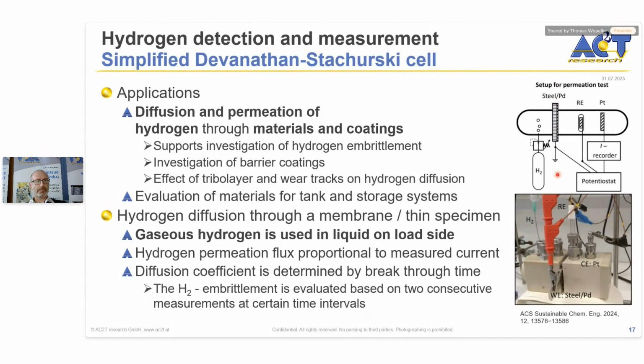And by measuring the electrical current between the steel electrode and the platinum electrode, you can determine the hydrogen content, which is proportional to the electrical current, and thereby you can determine the diffusion coefficient of the steel by determining the breakthrough time through the steel membrane. So the time the hydrogen needs to diffuse through the steel is an indicator of the diffusion coefficient.